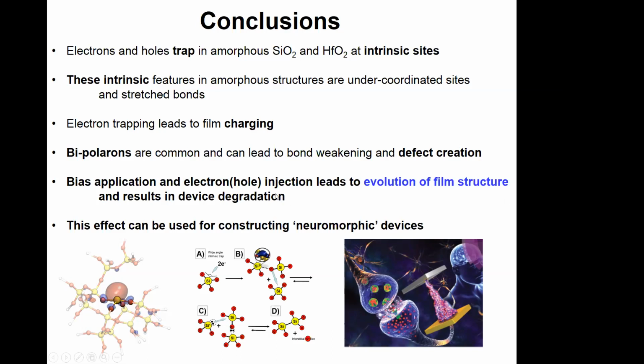And the preparation of these amorphous samples, you said you probably do the calculations on 200 amorphous samples. How much different are the results if you go from one amorphous structure to the other? Well, that is normal statistics, right? If you have fewer atoms, you have bigger fluctuations. Therefore, we need to find some balance between the size of the cell and the number of systems which we need to look at. Usually we deal with several hundred atoms in this type of system.